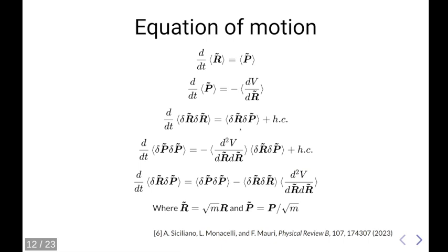In this way, we only have to rely on forces to integrate the equation of motion. For a wave packet, we generate a set of random structures, like 500, distributed according to the Gaussian distribution of ions. We compute energy and forces, essentially forces for each of these calculations, and then we can do one step of the dynamics, and so on and so forth.